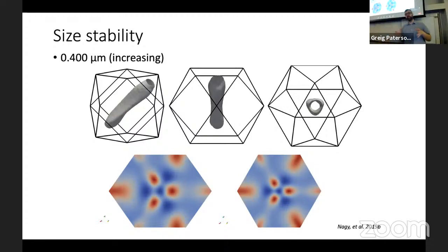However, as we keep increasing the size, something is beginning to happen to the domain structure. You can see on the grain on the very left that these edges are beginning to form, and the top right image is becoming slightly more triangular. You can also see on the bottom images that those ellipses, which correspond to the vortex core, are beginning to stretch out and form egg-like structures.